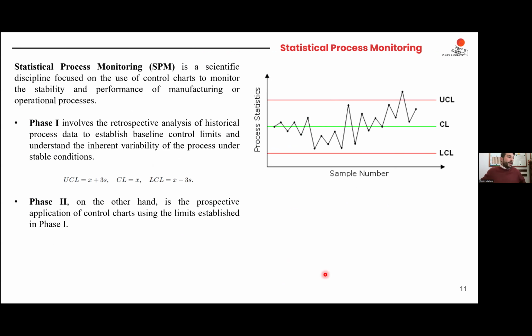And here there are some references that you can use to have a bit more details about what I'm speaking about. Now, once you have good deposition data, the traditional monitoring approach relies on control charts. So you are going to save the behavior of your process during the qualification procedure. And then you just consider one variable, for example, the mean value of the voltage, and you establish a medium line, that's the mean value of your process in stable condition, and based on the standard deviation, so the variability that your process showed during the qualification procedure, you can define bounds in the so-called phase one of the control chart.